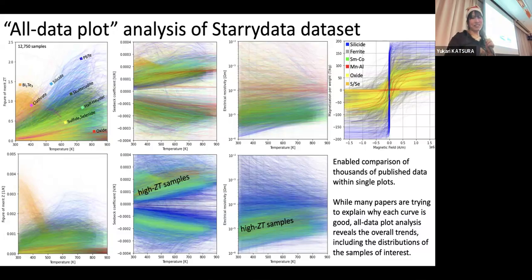improve the properties. But by collecting such papers, we can see these trends, and we can see where the high ZT samples are according to the other parameters like Seebeck coefficient or electrical resistivity. So without measuring all properties, we can find the promising samples just by measuring a single data point at room temperature. So if the electrical resistivity is around here, the sample will be promising. So you may synthesize more samples and filter the promising samples and carry on the experiment. So you can have more chance of success.